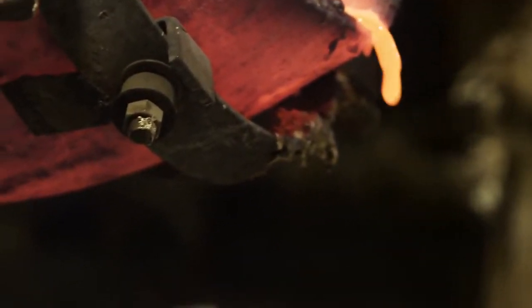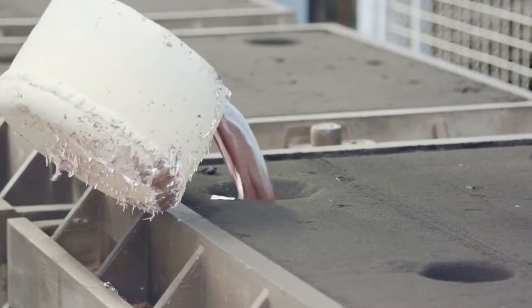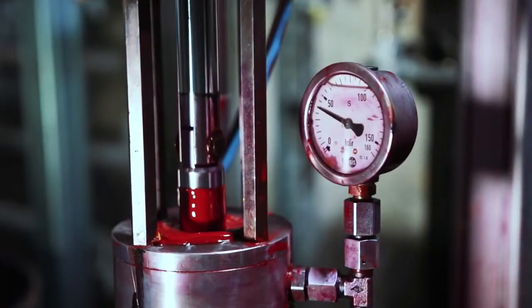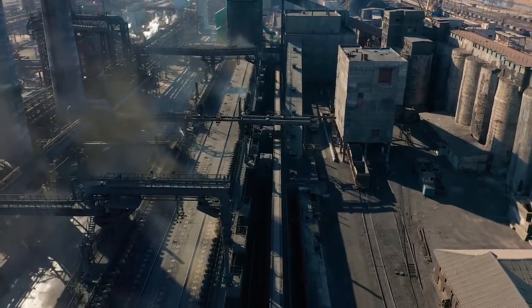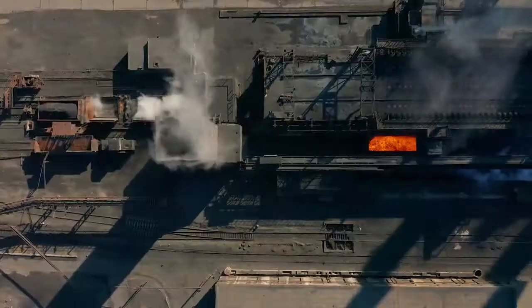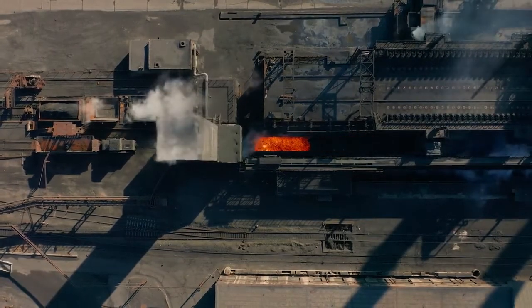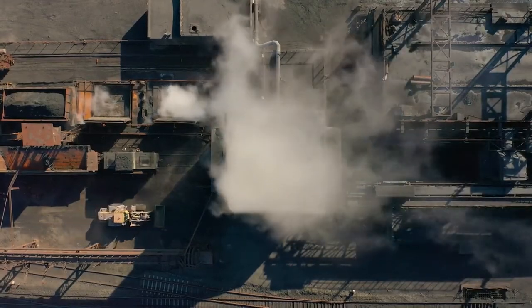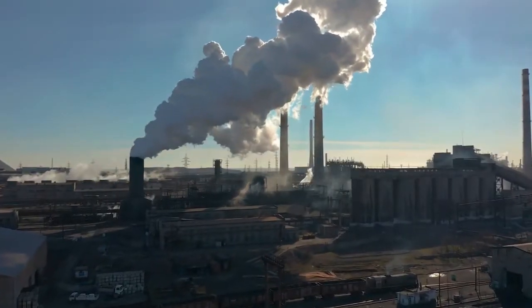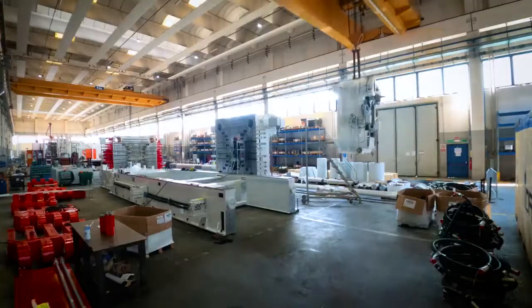Components and devices. The GigaPress resembles a die-casting apparatus rather than a machine. It has all of the necessary machines and mechanisms for die casting. Tesla's GigaPress has the following components. Ovens. The aluminium alloy is handled by two ovens in the GigaPress. One is a melting oven that runs on natural gas and has a temperature of 850 degrees Celsius. Another oven, which is powered by electricity and runs at a temperature of 750 to 850 degrees Celsius, preserves the liquid metal.